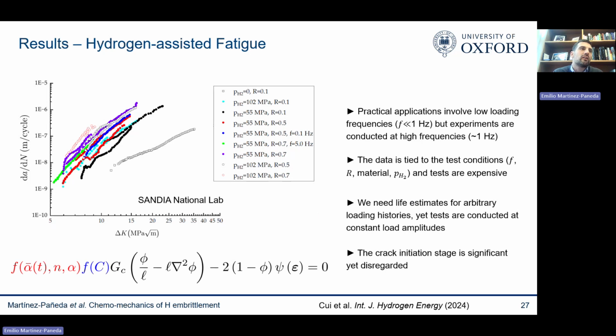So we try to model this, and the way you do that is basically you add a fatigue degradation function that has a variable that accumulates with your cyclic history and degrades your fracture toughness. This fatigue degradation function has 2 parameters that basically characterize how susceptible your material is to cyclic loading.